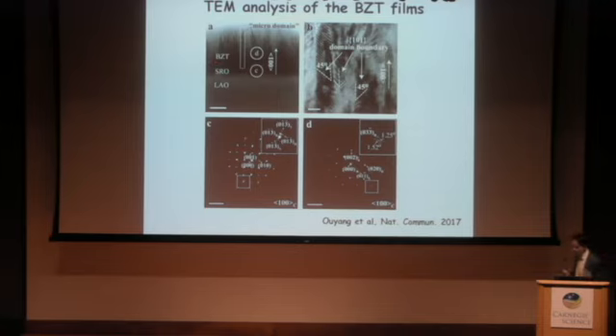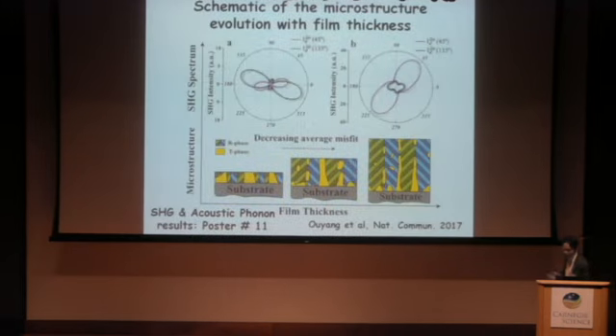So with this information, we did some second harmonic generation study. By the way, we have very intensive second harmonic generation results presented in a poster, and feel free to take a look. And we also have some nice acoustic phonon results there. But here, basically we took the depolarization second harmonic generation signal, and the intensity of this signal indicates the volume ratio of rhombohedral. The higher the intensity, the more rhombohedral phase you have.